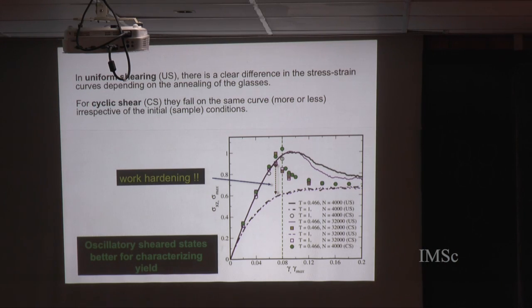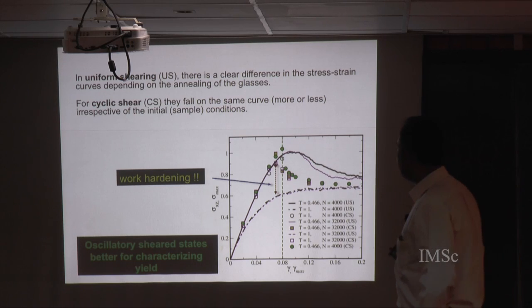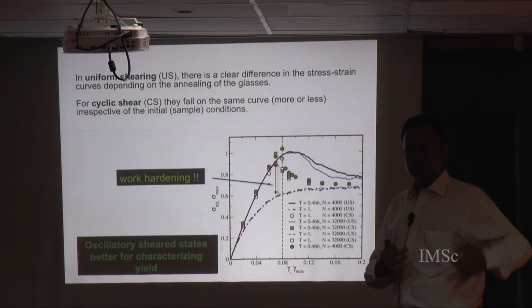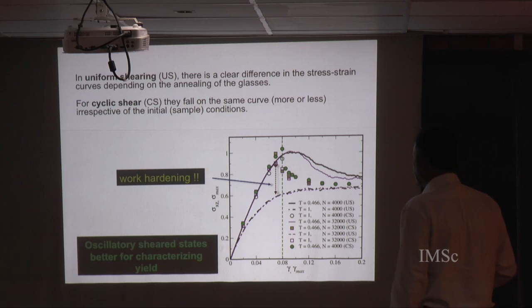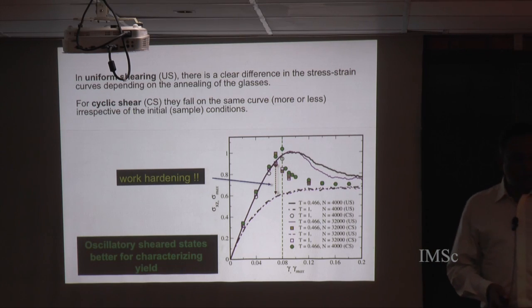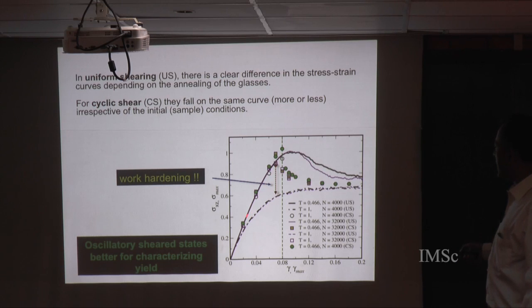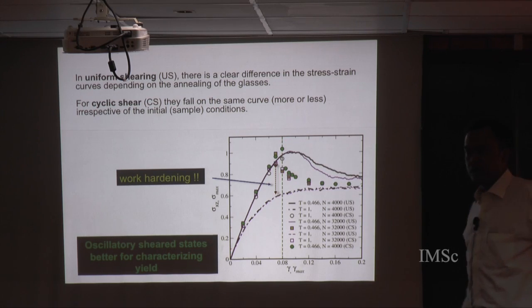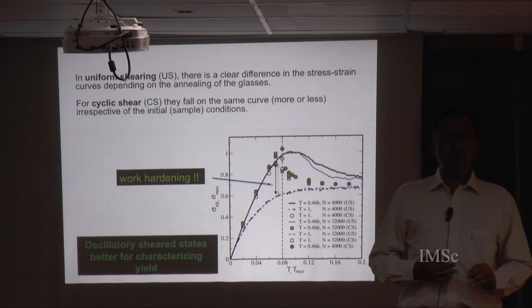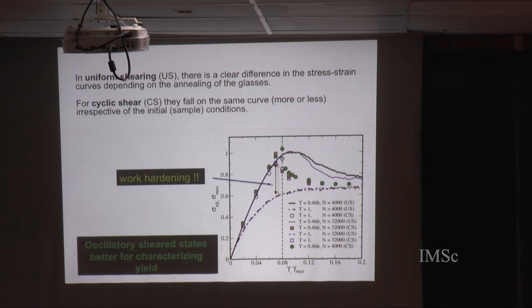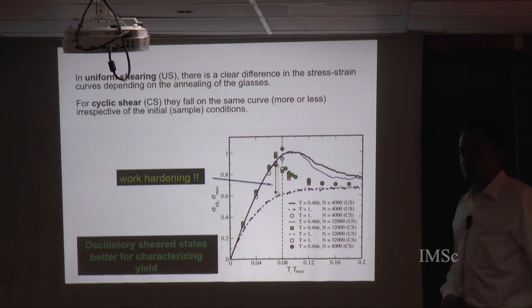It's a sharply defined transition, and interestingly, if you look at different glasses and different system sizes, even with minor variations, the behavior is very similar: to a first approximation, the stresses below and above yielding behave similarly both quantitatively and qualitatively, displaying this discontinuous jump at the transition.